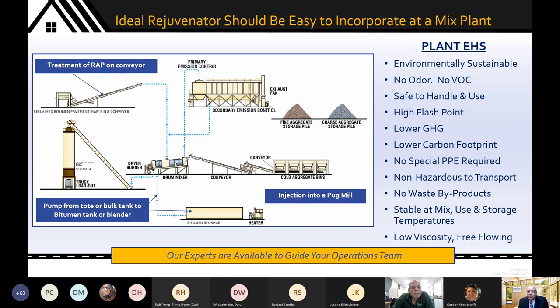Having done that, how would you incorporate it in a plant? And the answer, again, depending on the type of rejuvenator, is you could possibly introduce it at many points. Again, it all depends on whether it's free-flowing, whether it's non-toxic, and things like that. You could treat your RAP on conveyor. A challenging operation, but nevertheless can be done, and certainly must be done in the case of 100% RAP. If all you're doing is making 40% RAP mixes all day long for 3 weeks in a row, you could just dose your bitumen tank, stir it, and away you go. If you're making different RAP mixes, 30% for 6 hours, 60% for the next 8 hours, and so on and so forth, you need a little bit more flexibility.